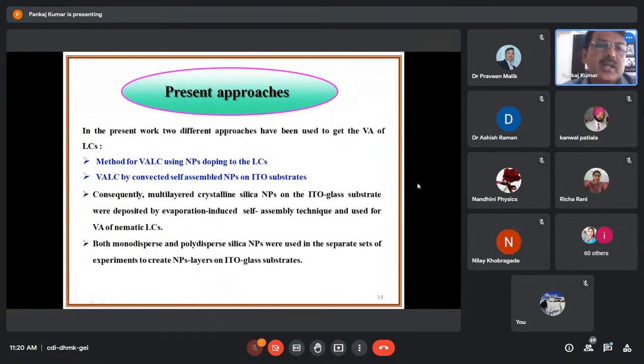So in the present work, two different approaches have been used to get the vertical alignment of liquid crystals. First is the method for VALC using nanoparticle doping, and second is the VALC by convective self-assembled nanoparticles on ITO substrate. In the first case, the nanoparticles were doped in the liquid crystal mixture. And in the second case, the nanoparticles were deposited with the technique known as convective self-assembly on the ITO substrate. Both techniques give very good vertical alignment of the liquid crystals, and I am very sure that these techniques will definitely be more useful for vertical alignment display devices, and companies will prefer these techniques to make the vertical alignment with the help of nanoparticles.